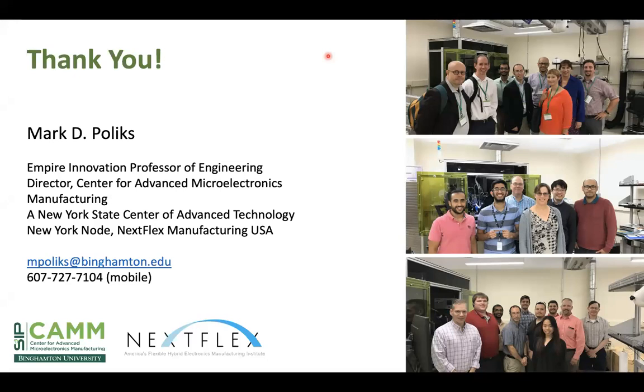And as we noticed, we do see drifts in resistance, but they're still within ohms, and that's still within a design point. So we're optimistic that this is still very much within reach. I think we're starting to see more and more of these applications emerge, and hopefully the work we've done and the work that others have done at NextFlex, and of course all the great work that you do, all the great work that's done in Europe and in Asia, is really moving the field in this direction. I think we're going to see a lot of good outcomes based on a lot of good research that's been performed to understand these surfaces and interfaces. As I like to call it, the interface between the hard and the soft is really what we're studying here.